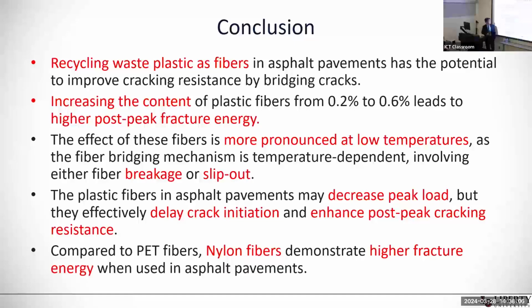So the conclusion here is that recycling waste plastic as fiber is very promising to improve the crack resistance if we choose the right dimension of the fibers and the right content of fiber in the mixture.